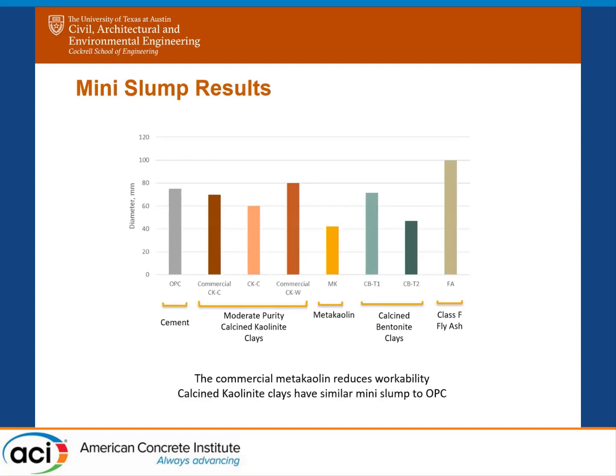We have OPC on the very left, and then the next three are all of the moderate purity calcined kaolinite clays. And then definitely the worst workability was metakaolin, which is expected, and then class F fly ash, the best influence on workability. So for those two in particular, you wouldn't really use 30% replacement traditionally, so the results are a bit inflated there. But yeah, this just shows that the calcined kaolinite clays have similar mini slump to OPC, so wouldn't have that major impact on workability that you see traditionally with metakaolin.